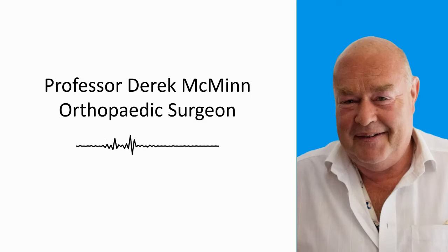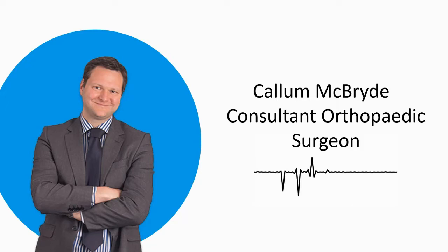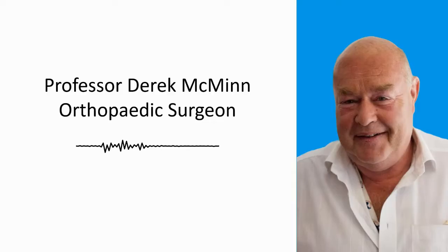But it all went to pot during 1996 because the manufacturer decided to double heat treat the metal with hot isostatic pressing and solution heat treatment. These are processes generally used in cast stemmed implants to get rid of porosity and minimise fracture, but they are absolutely deleterious for a metal-on-metal bearing. They either deplete or totally get rid of the wear resistors — the carbides — in the metal structure, which are essential for a well-functioning metal-on-metal bearing. Was there a feeling that there may be a problem with metal allergy or metal-on-metal wear? Because clearly it's now become a problem.